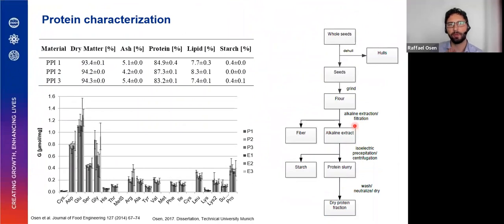We then looked into the composition as well as the amino acid profile to find some answers to that. Starting with the composition here on the top, we can see that it's rather similar for all three protein ingredients, with a slightly higher protein value for protein number 2, which would not really explain why we see this kind of difference in the extrusion behavior for that ingredient.